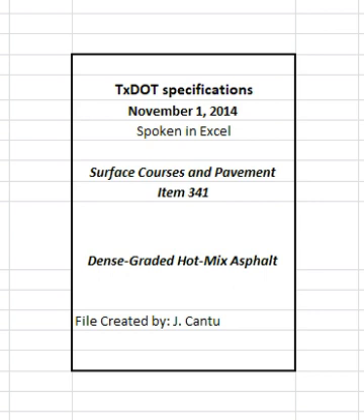4.5.2 Mixing and discharge of materials. Notify the engineer of the target discharge temperature and produce the mixture within 25 degrees Fahrenheit of the target. Monitor the temperature of the material in the truck before shipping to ensure that it does not exceed 350 degrees Fahrenheit, or 275 degrees Fahrenheit for WMA, and is not lower than 215 degrees Fahrenheit. The department will not pay for or allow placement of any mixture produced above 350 degrees Fahrenheit. Produce WMA within the target discharge temperature range of 215 degrees Fahrenheit and 275 degrees Fahrenheit when WMA is required.